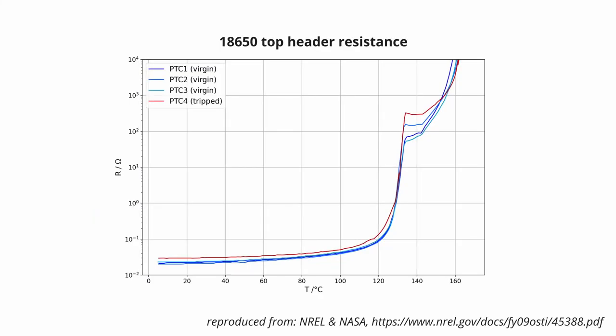One thing that you should know is that through repeated thermal cycles, the level of the low resistance state changes slightly. This can be seen in a graph showing an increase of the room temperature resistance by approximately 50%, meaning the device will become more sensitive once it has been triggered.